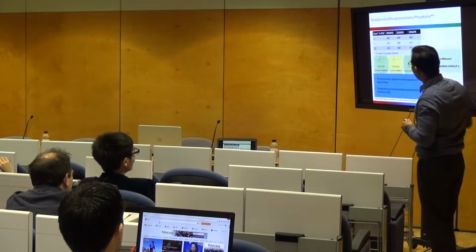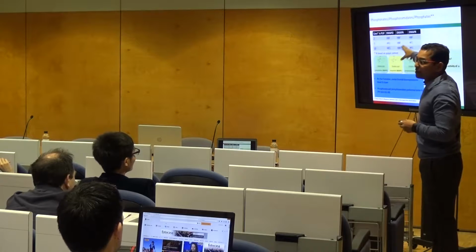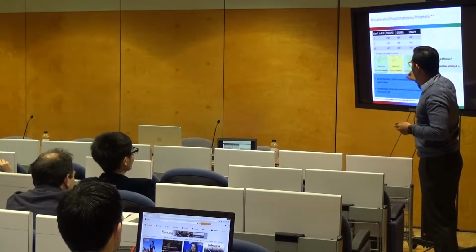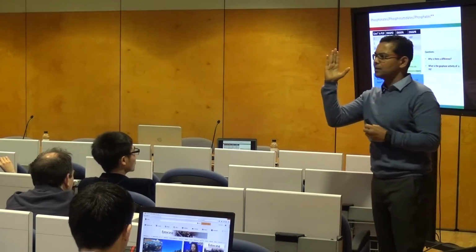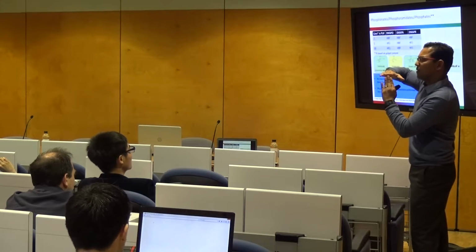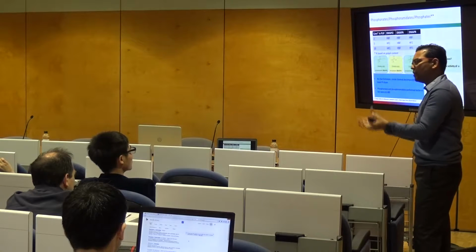I'm not going to show you the details, but look at just one comparison. Okay, you can see phosphate in the middle, and the ratings in the middle are the worst rating compared to the ratings on the side for phosphonates and phosphoramidates, I would say. So it's a UL 94 test. So instead of having a vertical test, it's a horizontal test. So you put the flame on a horizontal material, which is a foam, and you look at how it burns, okay? If it drips, if it burns the cellulose, then you actually have no rating.